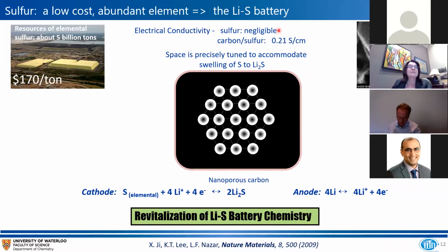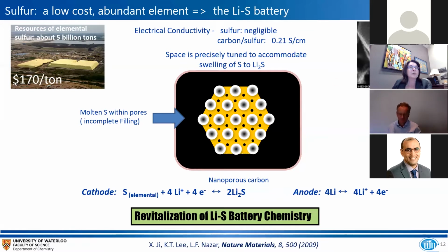So they have negligible electronic conductivity. So long ago in 2009, we developed this nanoporous or mesoporous carbon. You can see these are little carbon rods effectively, and they're on the nanoscale, 10 nanometers or so. And so we arranged these in these little sheaths and then effectively incorporated molten sulfur into this arrangement, this array